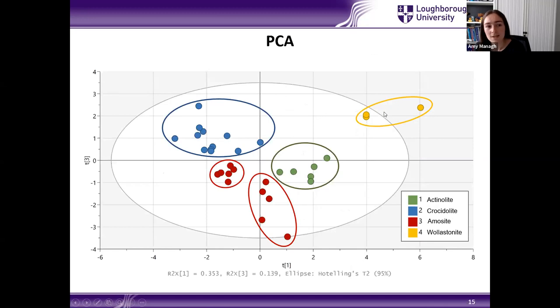We can also look at this data in two dimensions as well. And you can see that there's five different clusters within this data. Again, our wollastonite fibres are well separated. And we can also see the actinolite fibres in green and the crocidolite fibres in blue. Our amosite fibres, though, separated out into two distinct groups. And again, this showed in the cluster analysis that we performed separately.